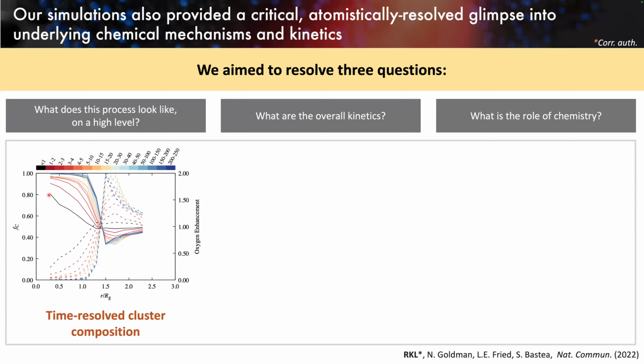We see at early time we have this mixture of carbon and oxygen, and as time goes on, we become increasingly pure carbon at the interior. We're pushing out oxygen, and we see that oxygen start to form an enhancement layer on the surface, consistent with that qualitative picture I showed you earlier. So again, we can characterize the kinetics of purification of these carbon nanoparticles.